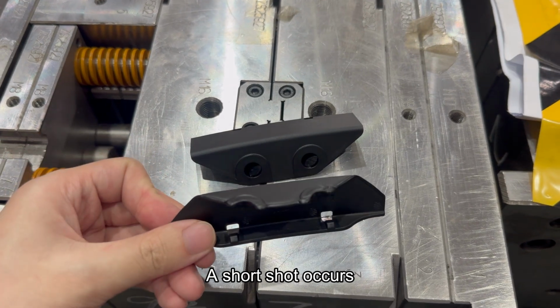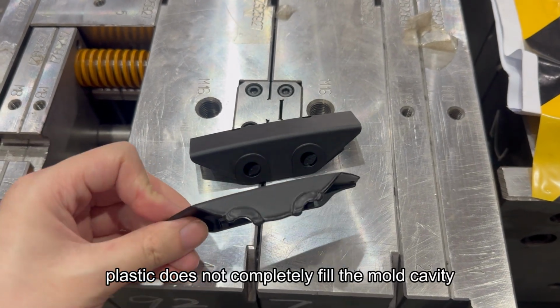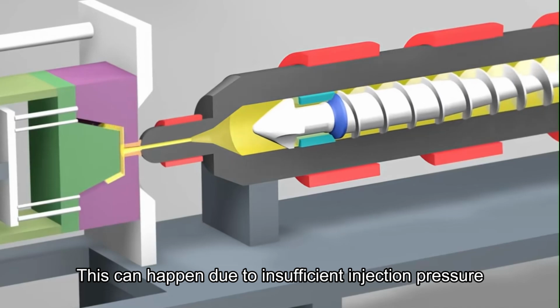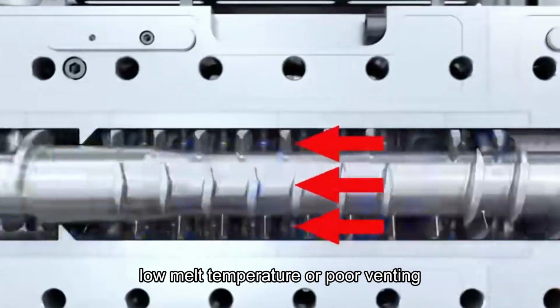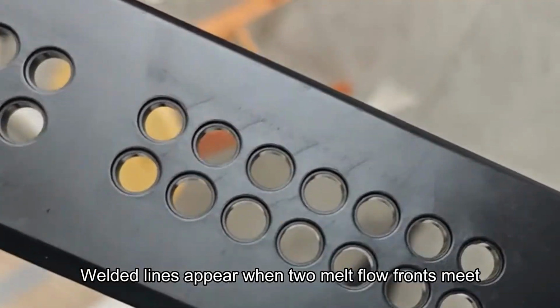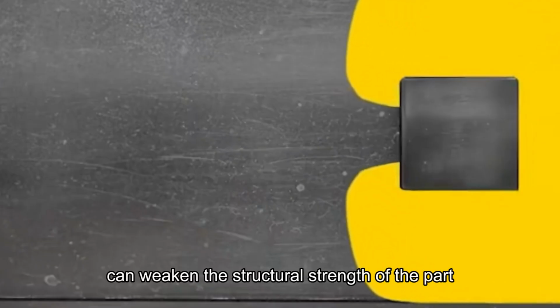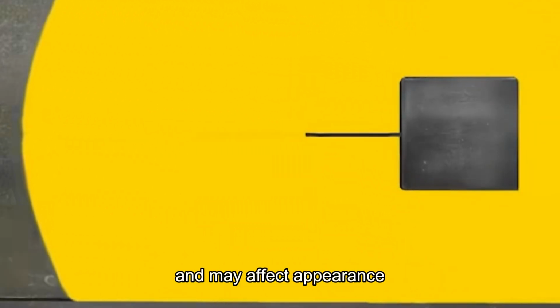A short shot occurs when the molten plastic does not completely fill the mold cavity. This can happen due to insufficient injection pressure, low melt temperature, or poor venting. Weld lines appear when two melt flow fronts meet but do not fully fuse together. These lines can weaken the structural strength of the part and may affect appearance.